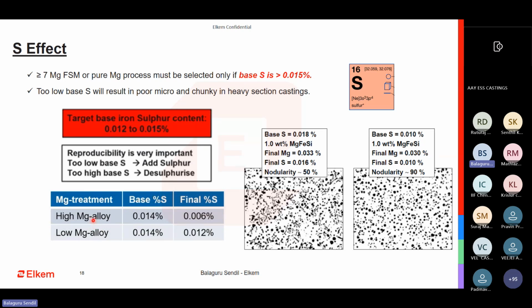If you are operating at 0.015, 0.016 in that range and using 8, 9, 10% magnesium alloy, most of the magnesium that you are having is going to eat up the sulfur, desulfurize it. You will end up seeing very small final sulfur in your base. Your final residual sulfur will also drop. So after ductile iron treatment, from base to final, you see a drop in sulfur. The drop in sulfur also has to be very minimum. If there is going to be a drastic drop in sulfur, that also indicates that most of the magnesium you have used has just done desulfurization. It has not been useful for creating nodules. It has just done desulfurization, which is also not a very ideal case.